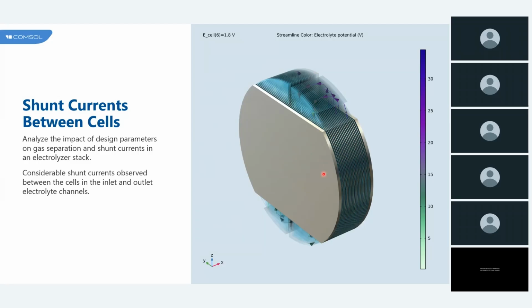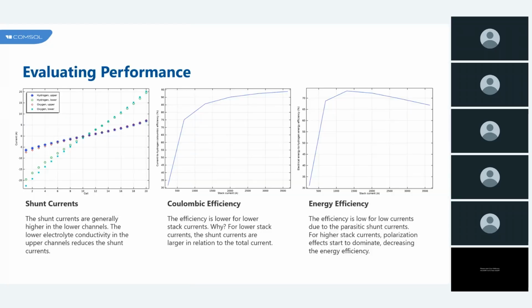So now that we understand where the shunt currents form, let's explore how they affect the overall performance of the system. To evaluate the performance of our electrolyzer stack, we focus on three key metrics. One is the shunt current. We track this across each cell operating at 1.8 volts, and the highest shunt currents appear in the lower manifold channels, which is driven by the strong voltage gradients and uneven electrolyte conductivity.